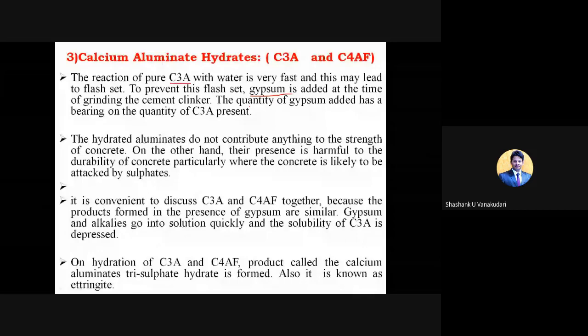The quantity of gypsum added depends on the quantity of C3A which is present. So depending upon the C3A present in the cement, the percentage of gypsum will vary, like 2% or 3%, so I say 2 to 3%. That is because of the total content of C3A in the cement. And here the hydrated aluminates do not contribute anything to the strength of the concrete. On the other hand, their presence is harmful to the durability of the concrete.